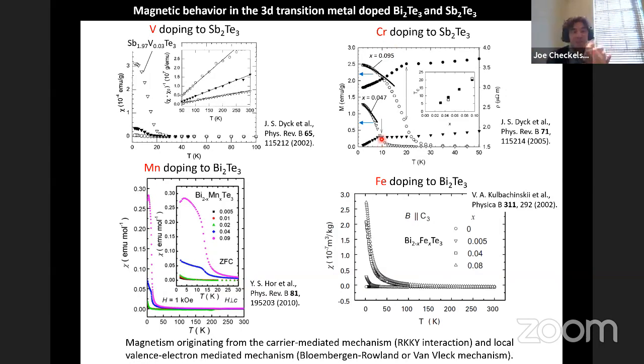Basically the way you do it is when you're grinding up your antimony and these powders together, you sprinkle in a little bit of some transition element. And as long as you grow the material in the right way, so that, for example, you can integrate chromium into antimony telluride, you can make a magnet with some reasonable Curie temperature, 10 Kelvin, 20 Kelvin, 30 Kelvin. So it was possible even early on to bring in magnetism to these systems.